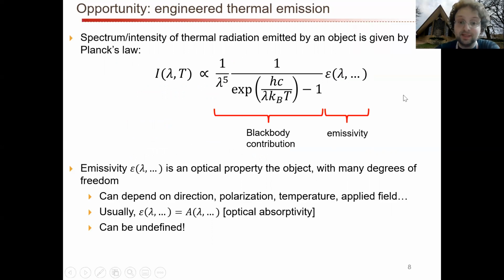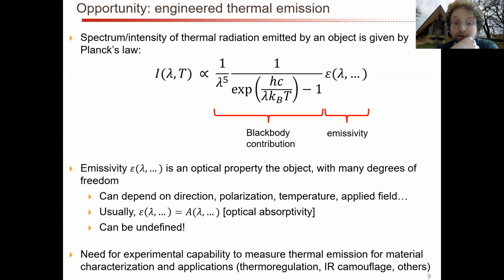Okay, so one thing that's worth paying attention to here that I think is a little bit less known is that this emissivity can easily be kind of an undefined or ill-defined parameter. That can happen under a number of circumstances, but broadly that happens when your object is not at thermal equilibrium. That means that the object is made up of a bunch of little pieces that are all different temperatures, or maybe the electron temperature and the lattice temperature are different and so forth. In all of these cases, this is not a well-defined parameter. You can't define the temperature very well, and therefore you can't define the emissivity very well either.